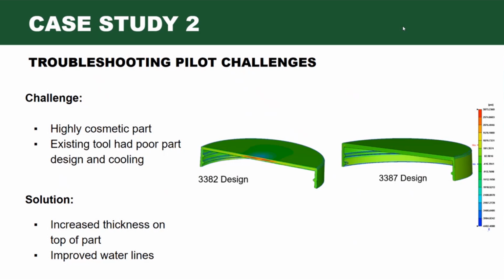But as soon as we got the tool and the design, we noticed, first of all, the part has a poor design. The side walls were actually thinner than the top of the part, which, because you're going through that corner radius, was causing the part to have a lot of splay and increasing the shear. So we asked the customer to keep it more uniform. We increased that thickness, and on top of that, we also improved the water lines.